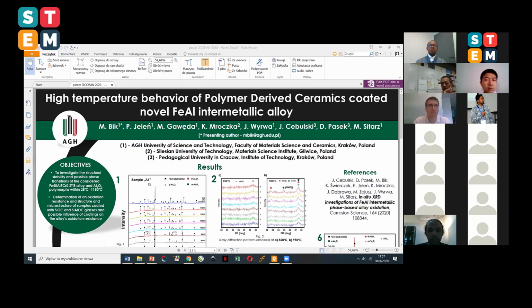Basically, in the past 40-50 years, scientists have been looking for heat-resistant light materials, and amongst these, alumina formers are of high interest due to the formation of a very thin protective, favorable layer of alumina, which is created on the top during the exposure of such materials to severe environment. And one of those alumina formers are iron aluminides, which can be characterized with extremely high oxidation resistance, not only to oxygen, but also to sulfurization, carburization, and nitridation. But there are some problems with hot workability and machinability, and with some tests at high temperatures about cycling oxidations and the problem of scale spallation.